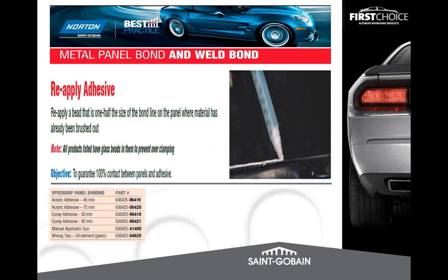Because just to give you an idea in strength, when we're talking about an acrylic, it's around 3,000 pounds per square inch tensile strength. An epoxy is about 2,000 pounds per square inch tensile strength, which is about the same strength as a spot weld. So you can see why acrylics are becoming popular. They're stronger than a spot weld, but also you can resistance spot weld through at any time during the process. So more and more OEMs are calling for an acrylic adhesive in addition to an epoxy. Even the F-150s are approved with the aluminum for both an epoxy and an acrylic, depending on the application and the job that you're doing.